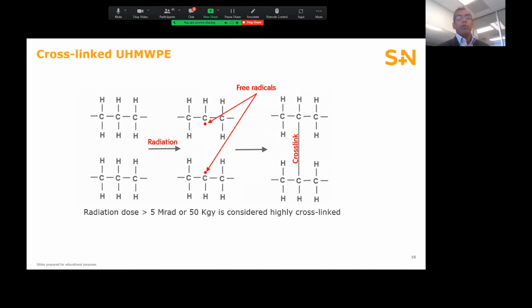A notable improvement was made to polyethylene in the late 90s with the advent of highly cross-linked polyethylene. Highly cross-linked polyethylene refers to polyethylene that's been subjected to an irradiation dose above 5 megarad. Irradiation breaks bonds within the polyethylene, creating free radicals. And adjacent free radicals can then combine, creating chemical bonds between adjacent chains. Any remaining free radicals can then be quenched through annealing or remelting of the material.